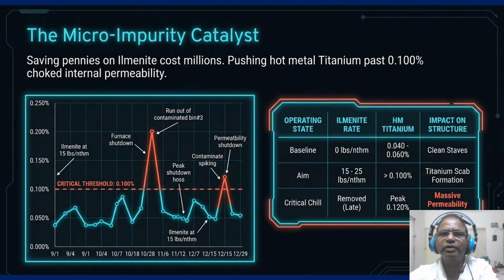When you run out of the clean bins and start using contaminated material, you are not just changing chemistry, you are physically choking the internal gas flow. This micro impurity acted as a catalyst for the mechanical paralysis. So never underestimate how a teeny decimal shift in an impurity can unravel the structural integrity of your entire process flow. The collapse of the chemistry and the structure is best understood through the PSPP framework of root cause analysis.